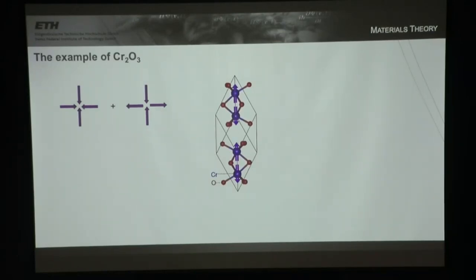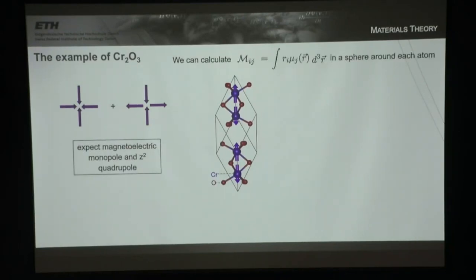The other thing, if I look closely, you see that my upspin chromium atom is shifted from the center of its oxygen octahedron in an up direction, right? It's not in the middle. So it has a local R, if you like. It has a local electric dipole. And the downspin chromium is shifted from its octahedron in the down direction. So it has a local electric dipole in the opposite direction. But mu times R, both up or both down, is conserved. Okay. So I haven't done any complicated group theory, just from thinking, I'm expecting a magnetoelectric monopole and a z-squared quadrupole. And we know how to calculate these things.